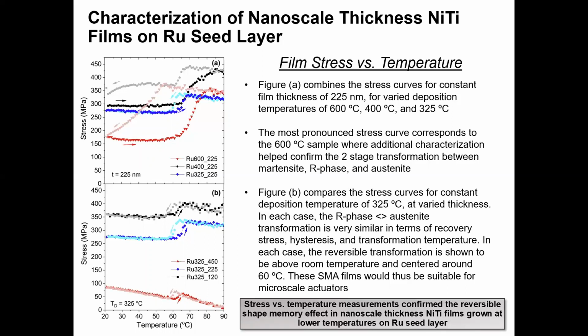It is. Yeah, and based on a variety of other characterizations we did, this film was undergoing the martensite austenite phase change, which is characteristic of larger recovery stresses. You're absolutely right with this larger hysteresis. And again, that was for the highest deposition temperature for a 225 nanometer thickness film.